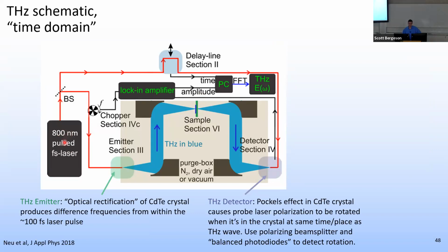Basically, you take an 800 nanometer pulsed laser and split it in half. You use one part of it to produce terahertz radiation. Terahertz is in between infrared radiation and microwave radiation, so you can think of it as infrared beams that have some microwave characteristics. This half produces pulses of terahertz radiation through what's called the optical rectification effect. The other part sends pulses into a detector, and through the Pockels effect is able to detect the terahertz radiation. So you produce terahertz, you detect terahertz, you put your sample in between, and then you can see the effects of the terahertz on your sample.